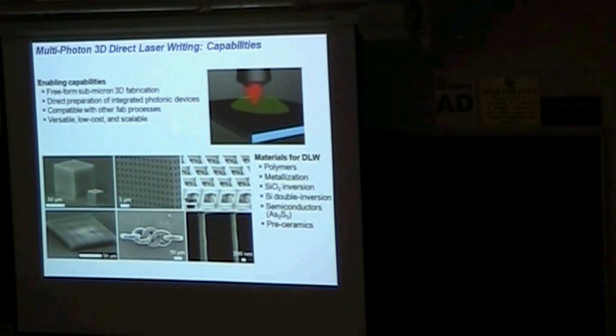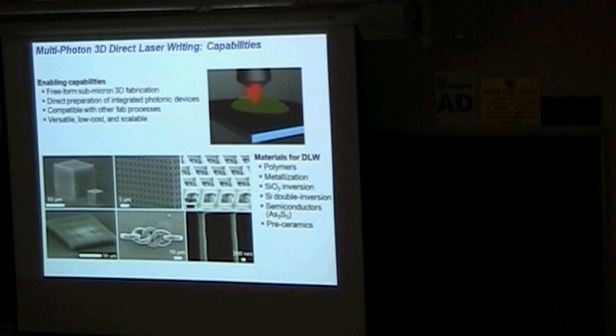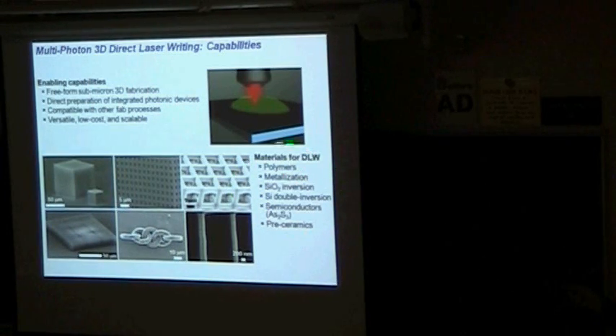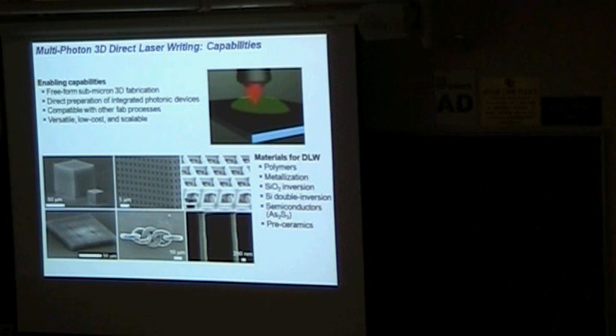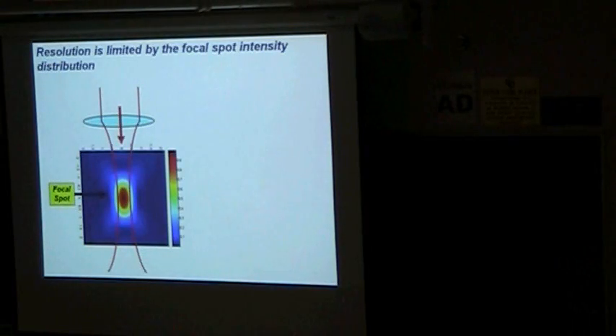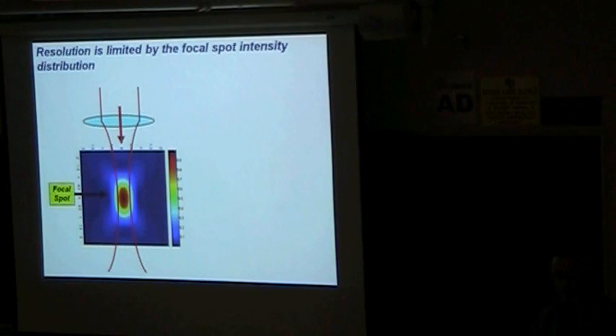The reason we got into this is we've done work similar to Rob McLeod's group, using multi-photon excitation for direct three-dimensional laser writing. We use a traditional single-beam method where localized excitation is limited by the diffraction-limited spot size achievable upon focusing with a high-NA objective. In my group we've used that to prepare photonic materials, photonic crystals, and we've contributed toward different material systems — specifically chemistries for metallizing polymeric lattices to transfer optical properties from dielectric to metal photonic crystals. This is a simulation using vector diffraction theory of the point spread function achievable under high-NA focusing with a 1.4-NA objective.